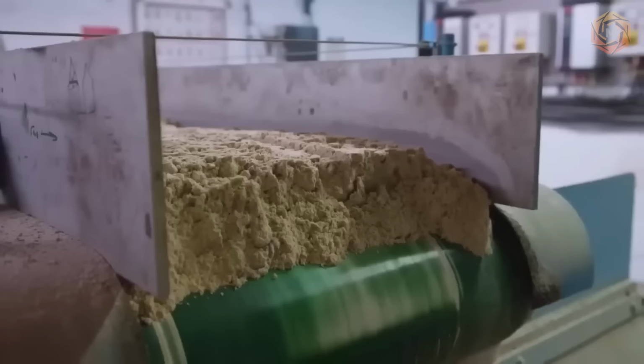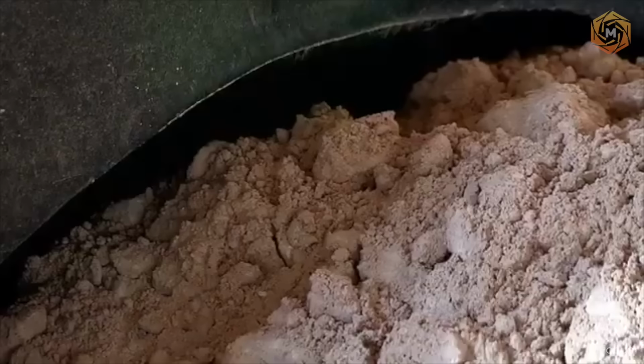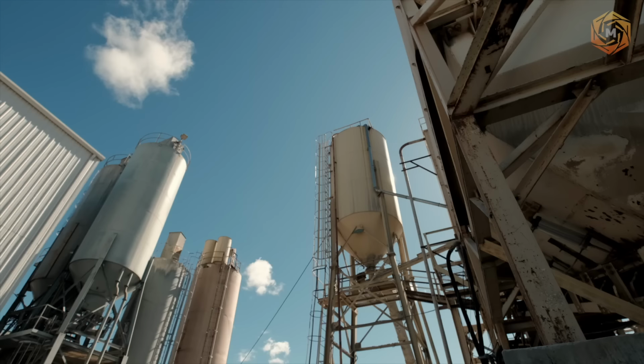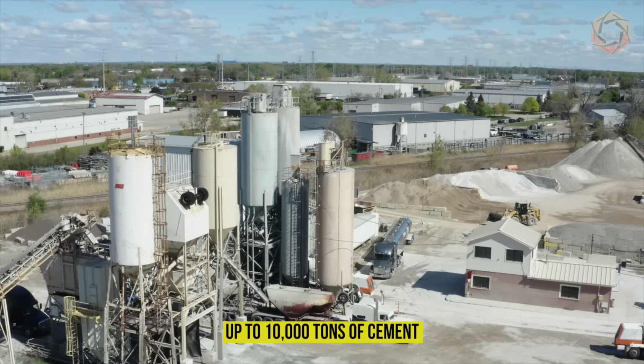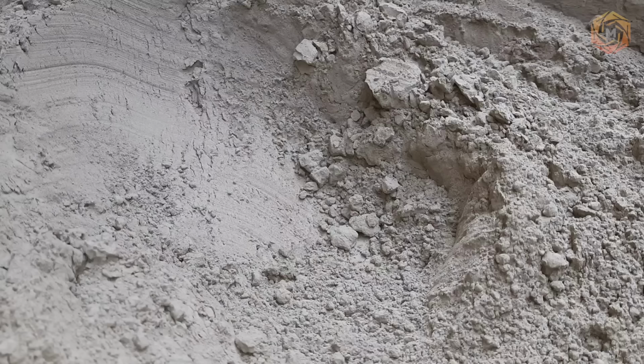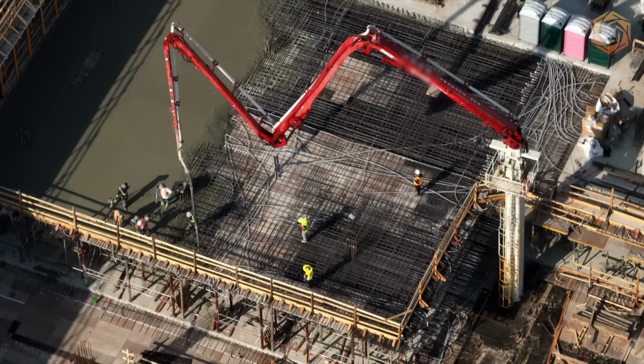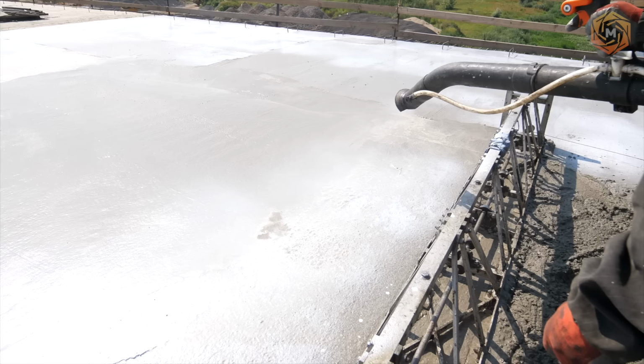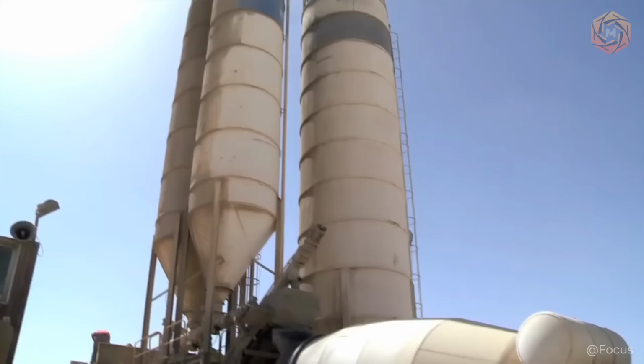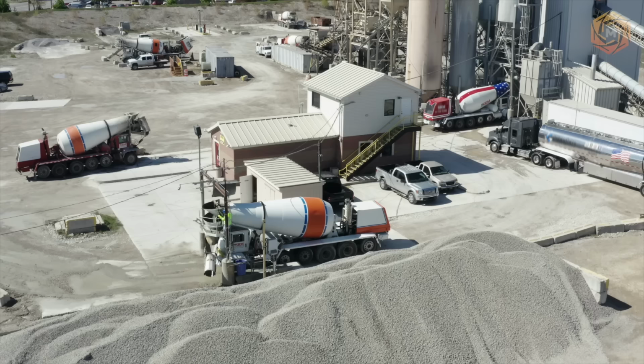After grinding, the resulting cement mixture is sent for storage in large reinforced concrete cans, or more simply, silos. They hold quite a lot, up to 10,000 tons of cement. There it cools down a little at a time, and the residues of free calcium oxide contained in it are quenched by interaction with air moisture. Thanks to this process, the technological properties of the finished material are greatly improved. Afterward, from the silos, cement is shipped to consumers in cement wagons, auto cement wagons, and covered railroad cars.